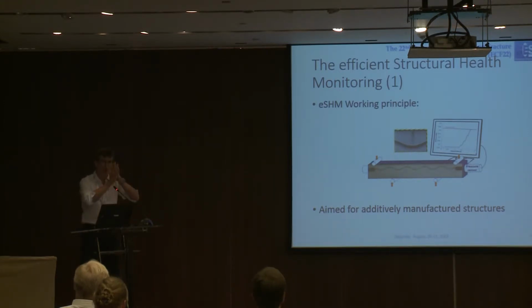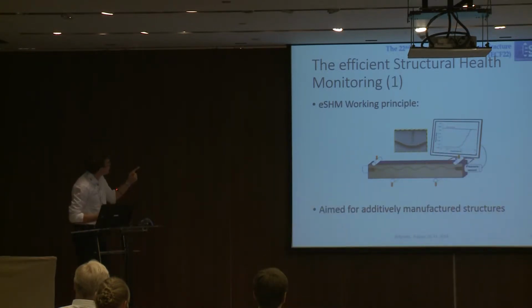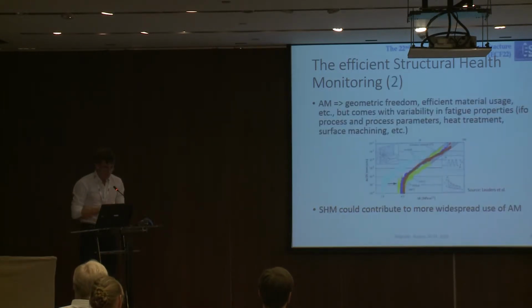And at that moment, while your crack is opening, it's actually making a connection between your capillary and the open atmosphere. And then, in this case, you have a sudden pressure rise in your capillary, and you know that there is a problem. Of course, as you need to have an enclosed capillary in your structure, you are more or less obliged to manufacture it by additive manufacturing, and you could think of it as a limitation of the system, but we see it the other way around in my lab.